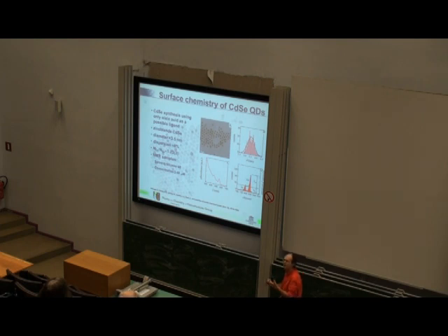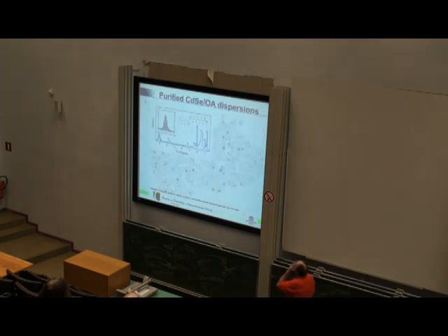I've mentioned these particles have the crystal structure of the bulk material. If you think of bulk cadmium selenide, for every selenium in there, you should have one cadmium. If you measure the ratio of the cadmium over the selenium in these nanocrystals, you find that they're not stoichiometric. Typically, they contain considerably more cations than anions. The ratio in the case of cadmium selenide here is something like 1.2, 1.3. Here we measured 1.23.